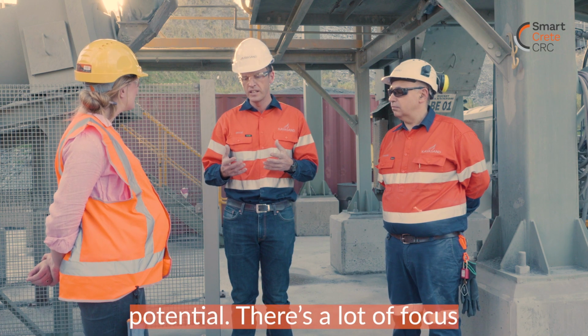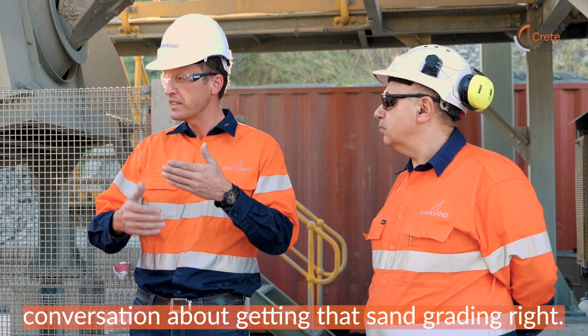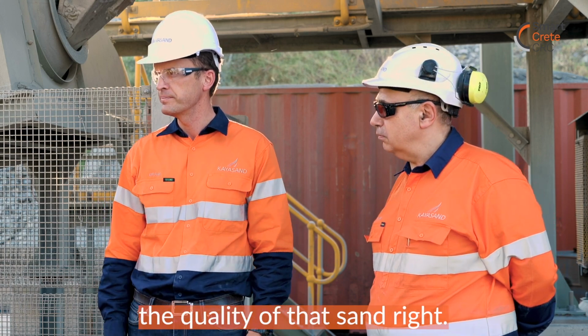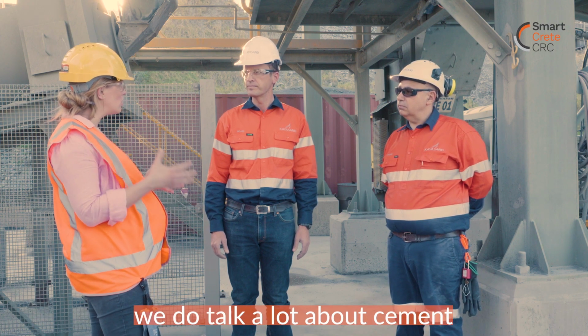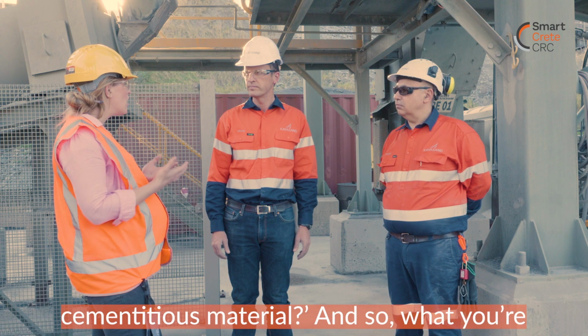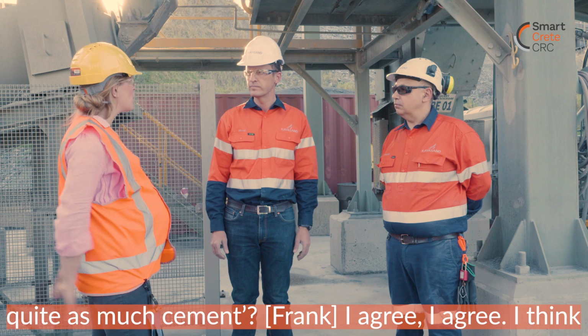Yeah. There's a lot of focus in the industry all over the world on supplementary cementitious materials, which is great. But what we want to provoke is more of a conversation about getting that sand grading right. We see a few people talking about that, but we see there's a lot more potential for achieving cement savings by getting the quality of that sand right. It's a very holistic look at the decarbonisation roadmap for the concrete sector, because we do talk a lot about cement reduction in our sector, but we're not necessarily talking about the ways to achieve that outside, say, a supplementary cementitious material. And so what you're bringing in is an alternative, which is let's think about the sand and the aggregate quality and how we get that denser particle packing so that we don't need to use quite as much cement. I agree.